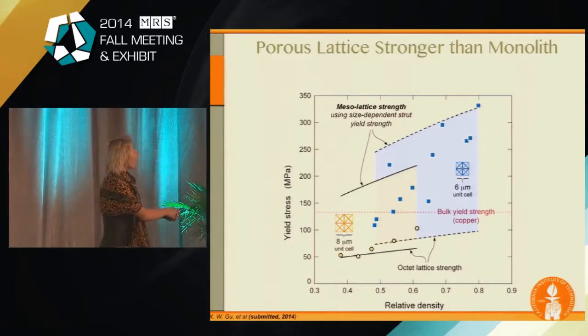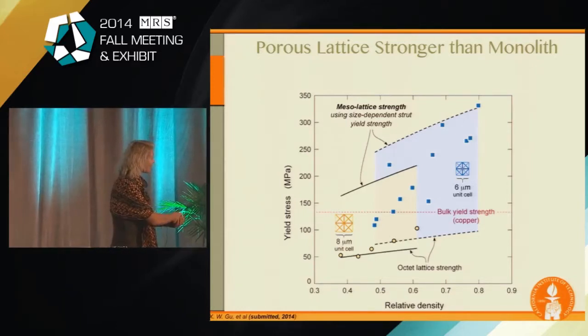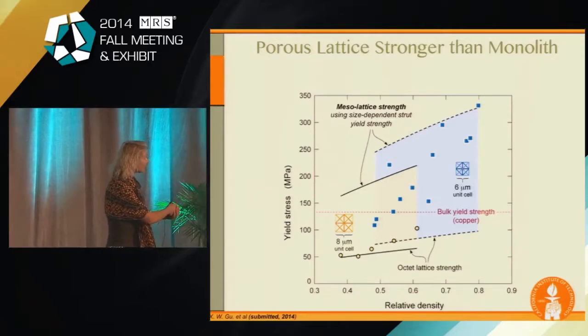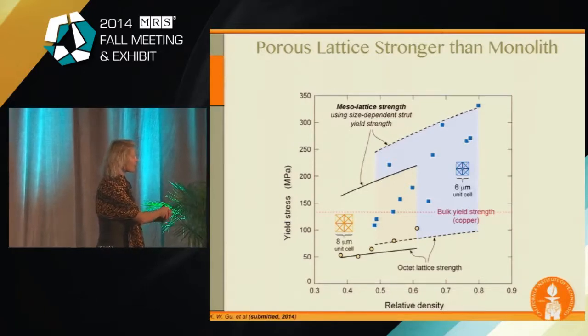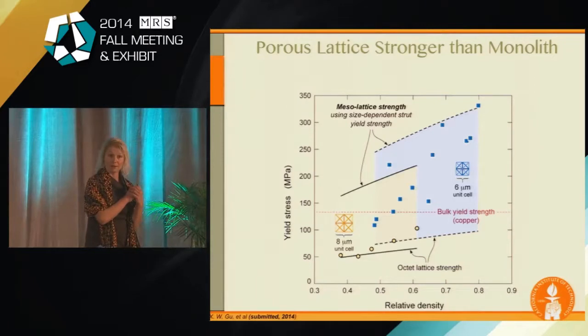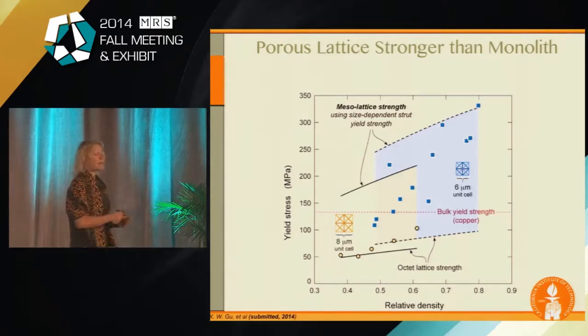So now, the size effect actually manifests itself in two ways here. These are the blue points and the orange points. These are all the data that Wendy took. You can see that at about 80% density, you already are getting structures that are much, much stronger than monolithic copper. But there's another thing. She made two different unit cell sizes. She made a 6-micron unit cell and an 8-micron unit cell.